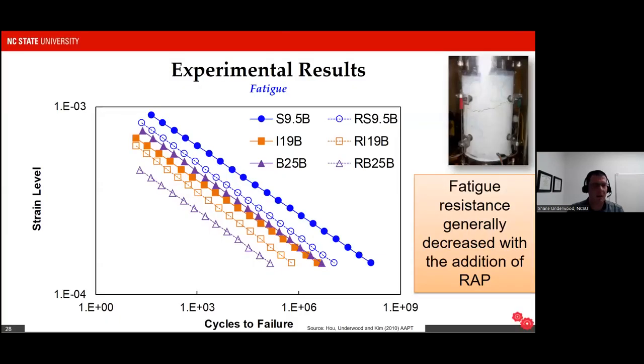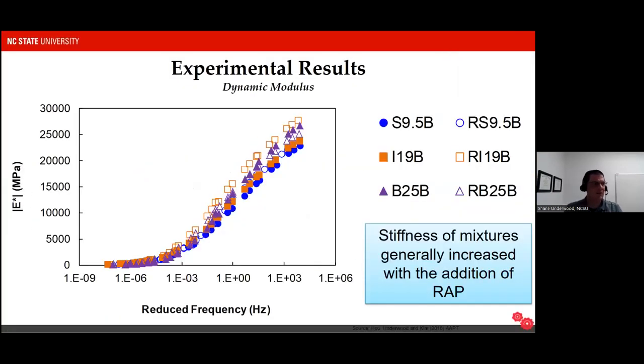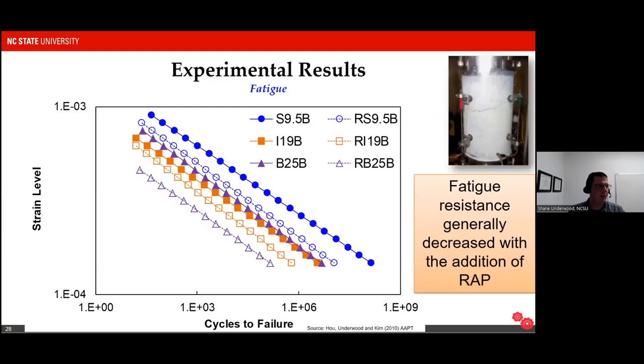So we saw that the stiffness was higher on the RAP mixtures. Now, when we look at fatigue, here we're looking at a typical fatigue S versus N plot. And basically what this tells us is at a given strain level, how many cycles to failure do we have? If the curve is positioned more to the left, that means worse fatigue performance. The further to the right our figure is, the better the fatigue performance is.